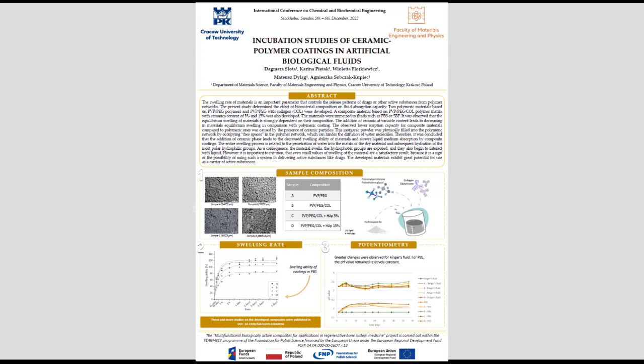After developing the composition and determining the purity of the components and the sedimentation rate, imaging was done on an optical microscope. In this way, the surface morphology was examined, and we also measured the thickness of the coatings. Since the coatings are a material with application potential in medicine, it was necessary to study their behavior in artificial biological fluids. During such incubation in Ringer's fluid and PBS, pH value changes were determined over a period of 40 days at 37 degrees.